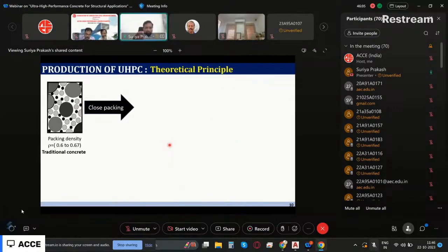Now let's look at a small sample of concrete under a microscope, and look at the size of the particles. The bigger sizes are your coarse aggregate, the small white substances are your fine aggregate, and the small dark ones are your cement grains. You can see that the white spaces are all the voids in the system. And how closely I can pack these particles is called packing density. If I can put more material within a particular cross section, and the white space is completely zero, then packing density will be 1. But it's very difficult to achieve because all these particles have different shapes. So when you put the different particles together, you cannot always fill completely, right?